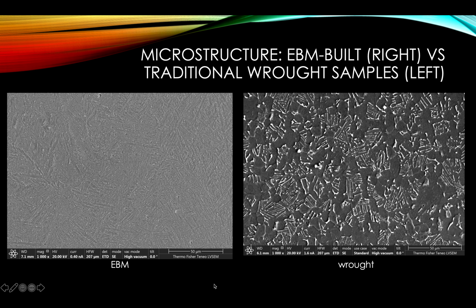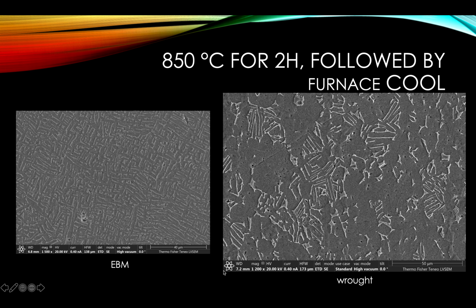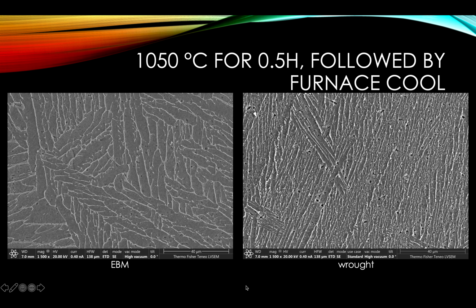For the EBM sample before the heat treatment, it has this basket weave pattern microstructure and acicular grains. The grain size is very fine. Well, for the wrought sample, the grains are equiaxed, and the primary alpha phase is mixed with this alpha-beta laminar pattern. After 850 Celsius for 2 hours soaking time, followed by furnace cool, the EBM sample still has this basket weave pattern, but changes its orientation from the previous triangle-like pattern to this square-like pattern. The grain size also becomes coarser.